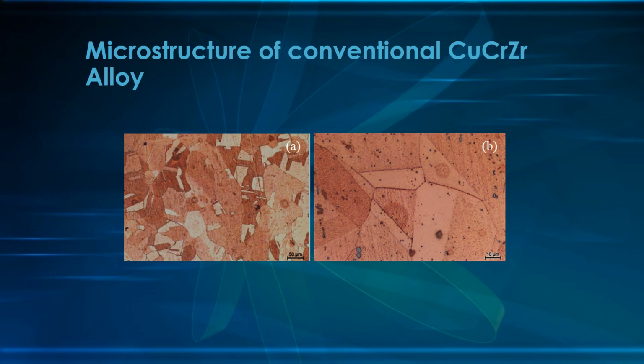So you can see that here the grains are more regular. We can notice the presence of twins, and in the micrograph on the right part of the screen you can see also those small gray phases, which are chromium rich phases formed during the solidification of the alloy.